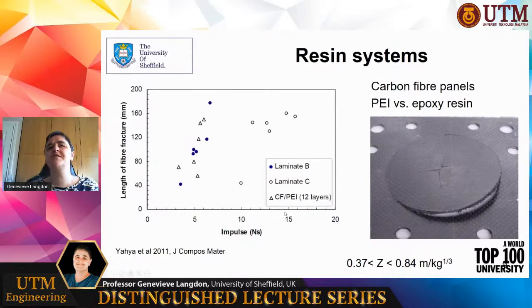The reason for that is that the fiber usually dominates over the resin in blast response, particularly for the stronger fibers such as carbon and glass and ultra-high molecular weight polyethylene. Where your fibers are weaker, like in a natural fiber, then you would see the resin contributing more to the blast resistance.